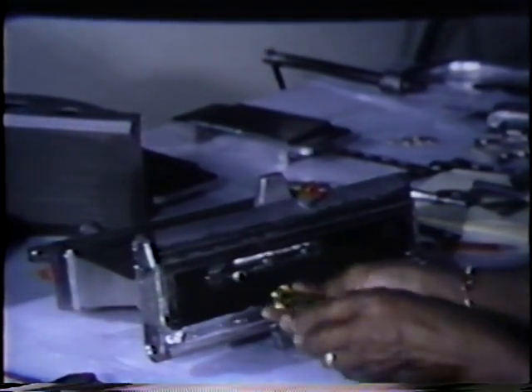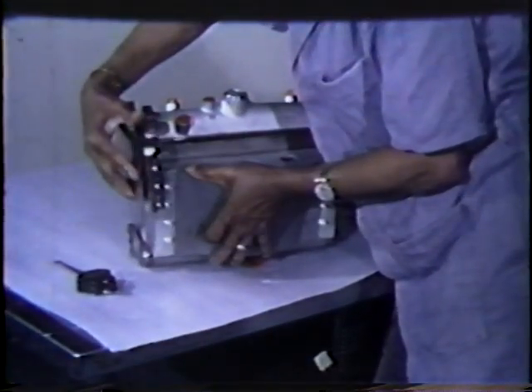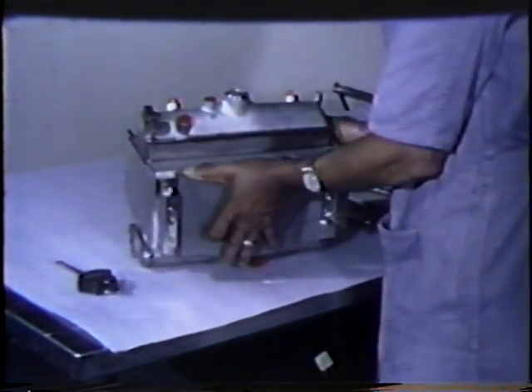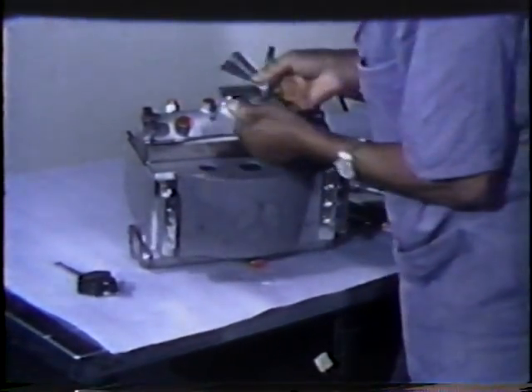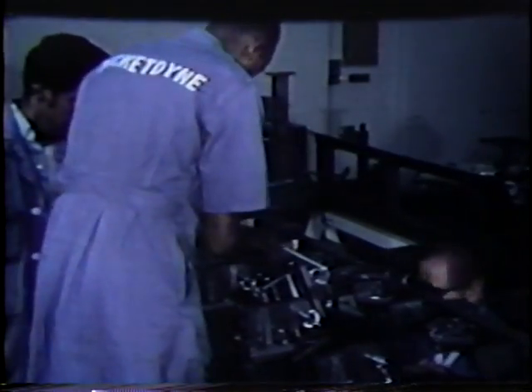Electron beam welding of the injector and dome assembly to the completed liner assembly is facilitated by inclusion of an edge inlay on the injector plate. Completion of the combustor assembly is achieved by adding backup structure to the segment and injector assembly. They are sand cast heat treated aluminum alloy units. They support the pressure loads along the sides of the cast liner for the length of the segment between the injector and throat end. The extensive use of mass producible castings in the combustor provides considerable cost savings during manufacture. Additional cost advantages are realized since manufacturing mortality exposure occurs on relatively inexpensive small parts.